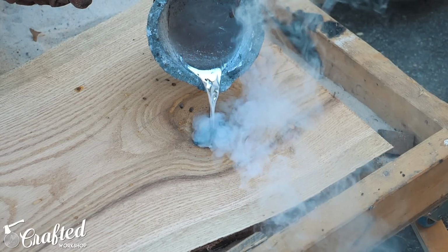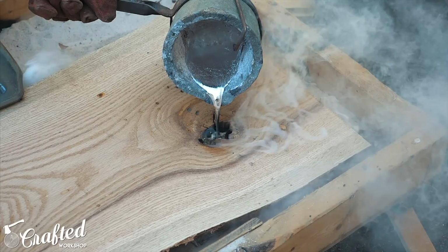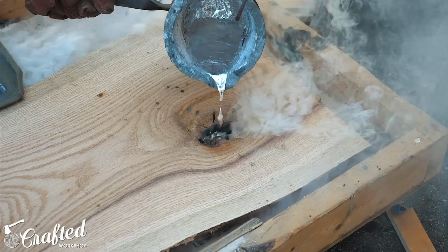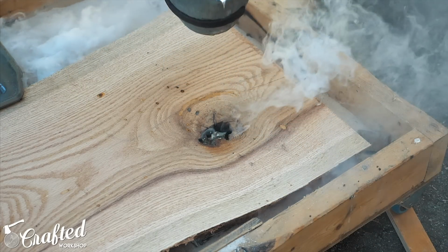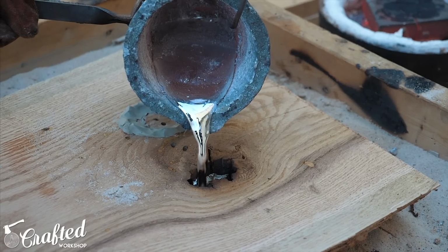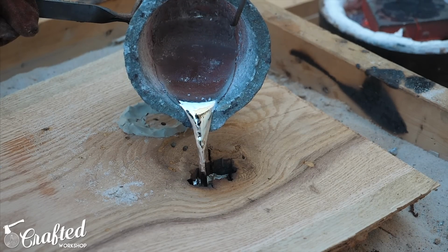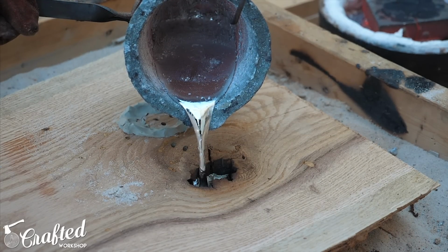That said, the first thing we noticed was that the aluminum was definitely leaking, and we figured that this was because the plate had warped due to the high heat from the aluminum. We let the first layer cool down just for a couple seconds just to kind of plug the hole, and then continued to fill it with more aluminum.